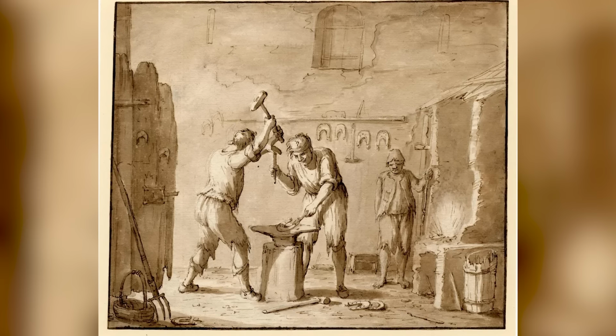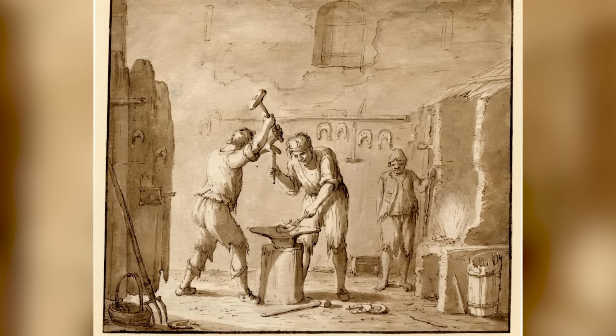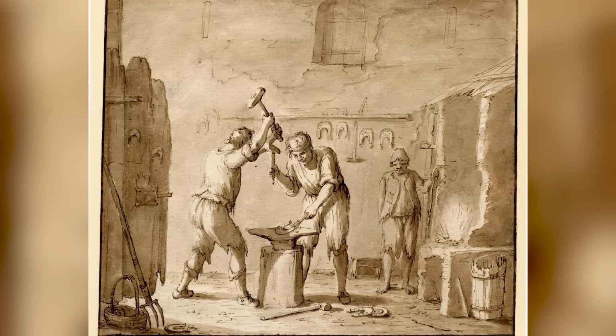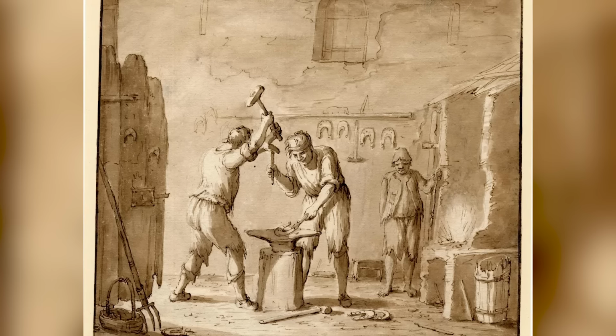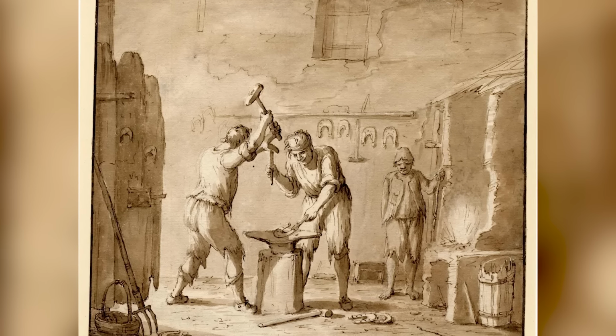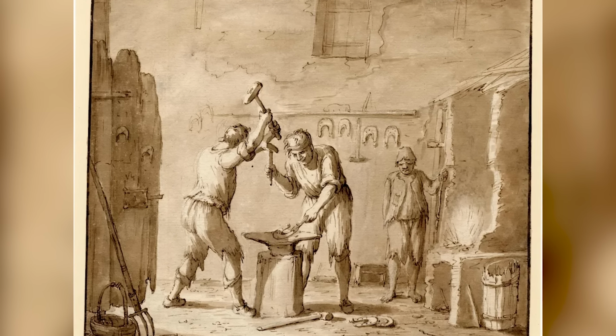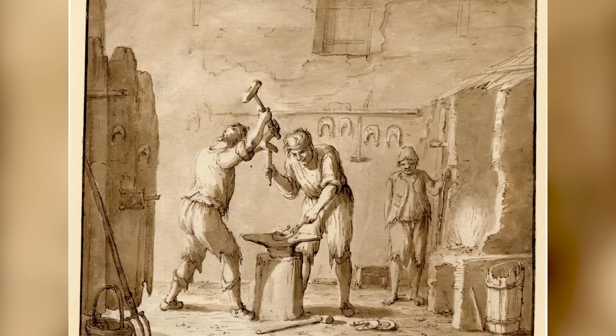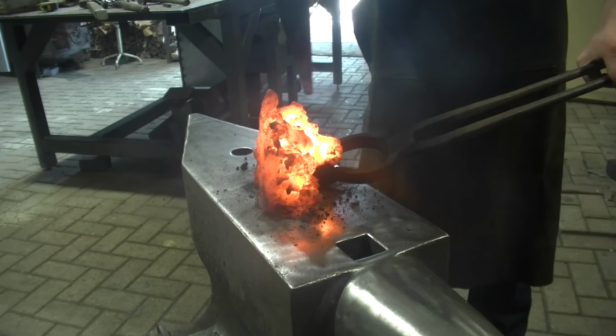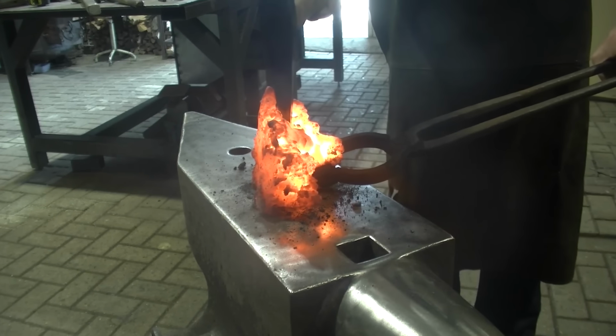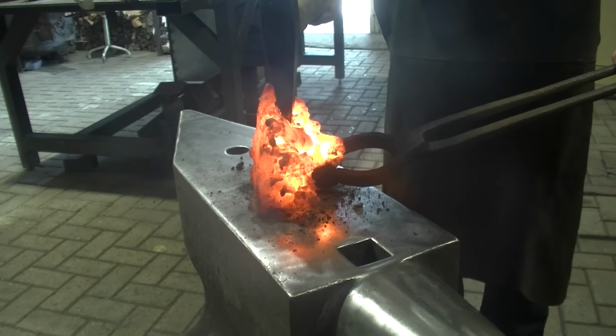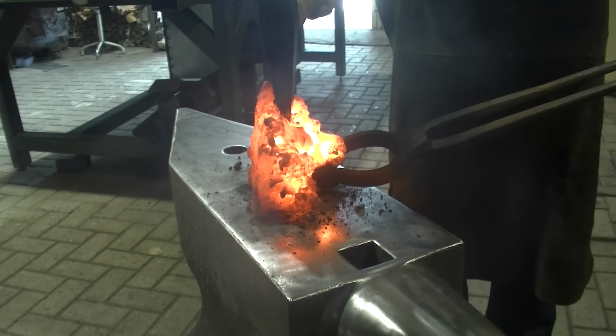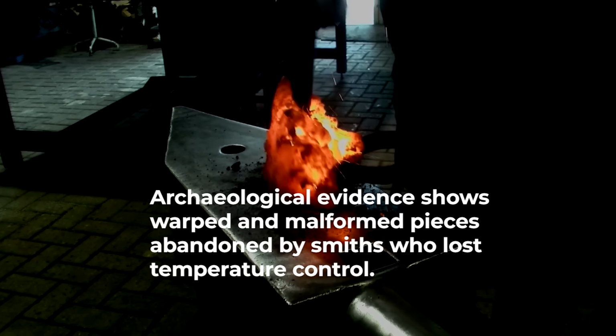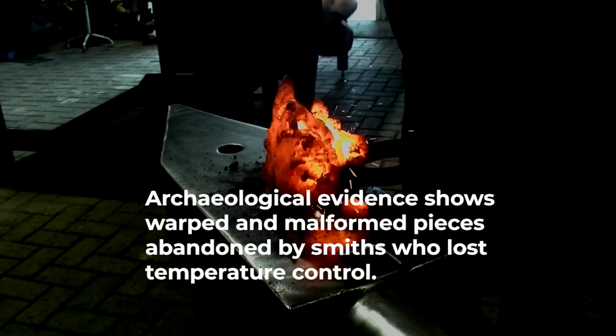When iron is struck at black heat, the hammer leaves visible cracks on the surface. The metal chips instead of deforming. Documented failures from medieval guild records describe tools that shattered on first use after improper cold working. When iron is worked at excessive yellow heat, the metal deforms uncontrollably. Shape is lost. Precision becomes impossible. Archaeological evidence shows warped and malformed pieces abandoned by smiths who lost temperature control.